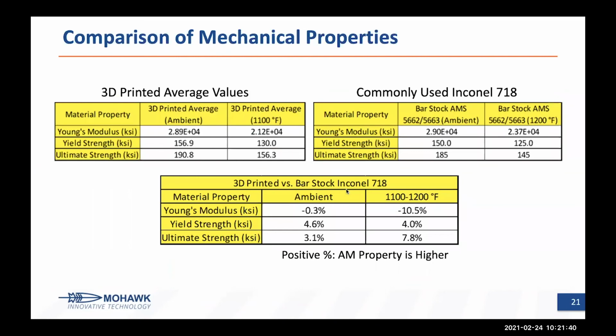If you take a look at the average of the mechanical properties, on the upper left table, that's for the 3D printed values. The first column shows the ambient room temperature, and the second column shows the 3D printed average properties at 1100 degrees Fahrenheit. We see about 29 million modulus for Young's modulus, yield strength of about 157 and 191 ultimate strength for room temperature. At elevated temperature, as expected, we see a degradation down to maybe 21 million modulus, 130 KSI and 156 KSI ultimate. Compared to bar stock Inco 718, you can see in the room temperature modulus, we're basically about the same.